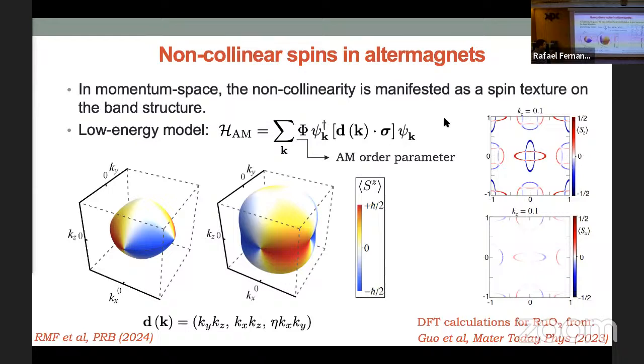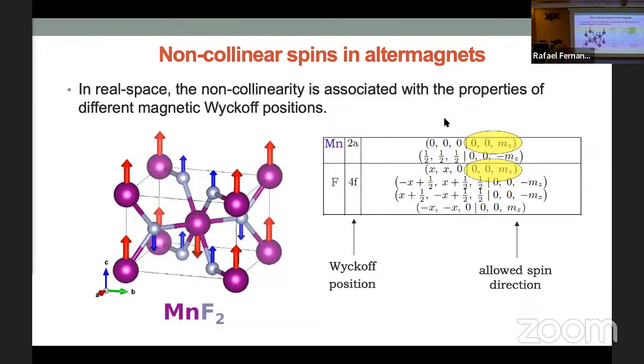Now, if you don't believe me, if you want to see this from first principle, here's a very nice DFT calculation on ruthenium oxide, not at k equals 0, with spin coupling, and you see that you do get moments that are not sigma z. If you're still not happy with that and you want to see real space, there's actually a very nice way, which is to look at their Wyckoff positions. So, manganese difluoride, you can look at the magnetic Wyckoff positions, and initially you say that I'm wrong.